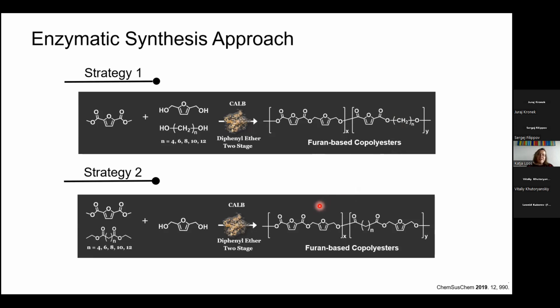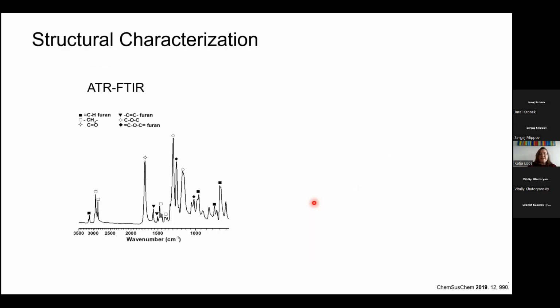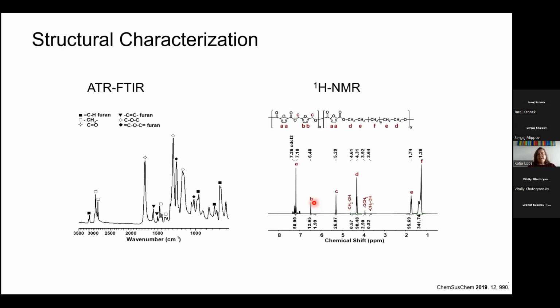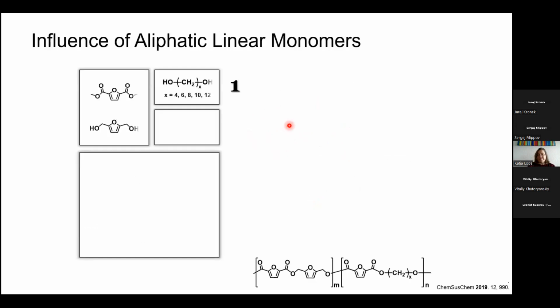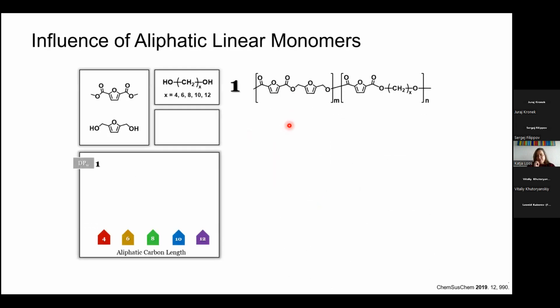And so we are approaching it somehow from the bottom. And this was actually really nice. So you see in the IR and the NMR that you can quantify that this structure that we want to have, and yeah, you can also increase it. And we also found that the different strategies have a different success, and this really comes from the mechanism I showed you in the beginning.